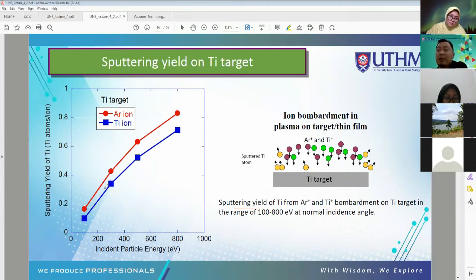So using this tool, we can evaluate the sputtering yield. You can see the sputtering yield from the argon ion and the titanium ion is not much different. So we can conclude that the ion bombardment damage comes from both elements, the argon ion and the titanium ion here. This is our conclusion on this part.